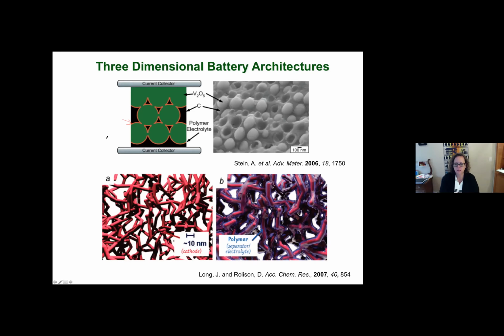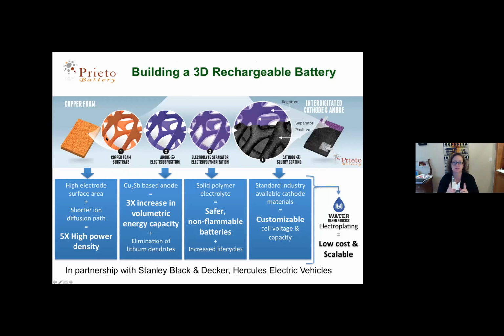So the take-home messages from these approaches is that it is very difficult to integrate different types of materials. But also the electrolyte layer is absolutely critical because for really high power, that layer needs to be very thin. It has to be electrically insulating and ionically conductive, and it needs to function as the separator as well as the electrolyte. So mechanically, it has to be quite robust. So I learned a lot about the challenges for each component from these two examples. And from that, we tried a variety of things that did not work, but then we arrived at this approach.